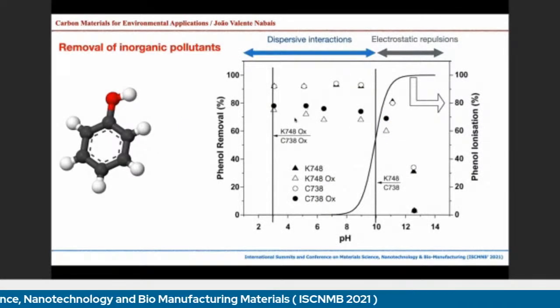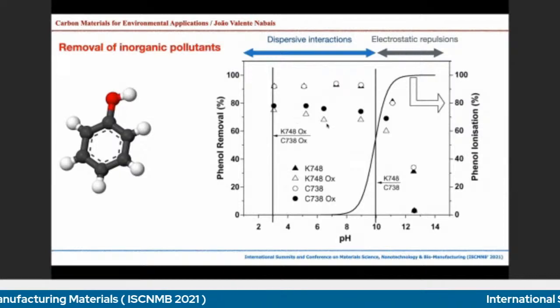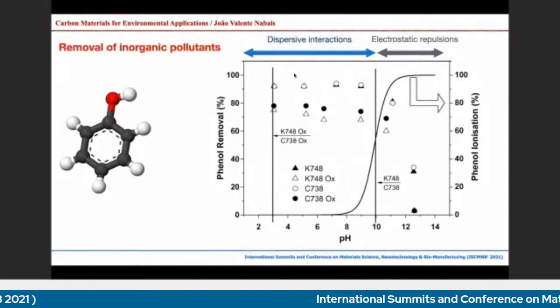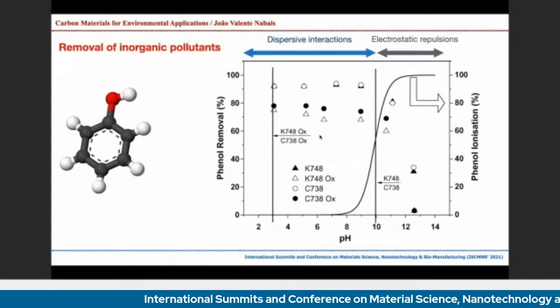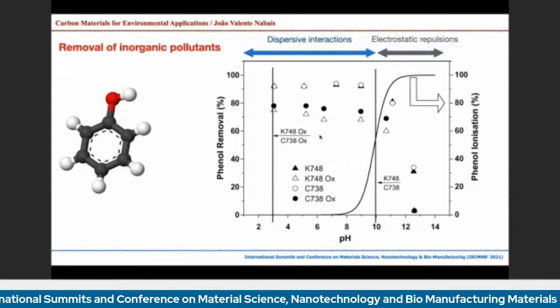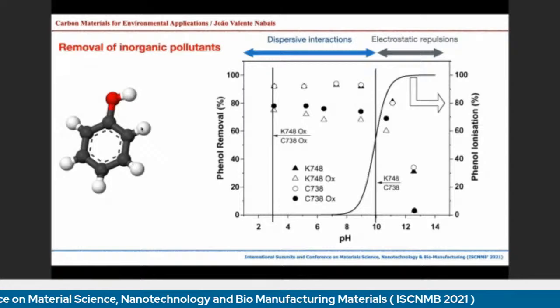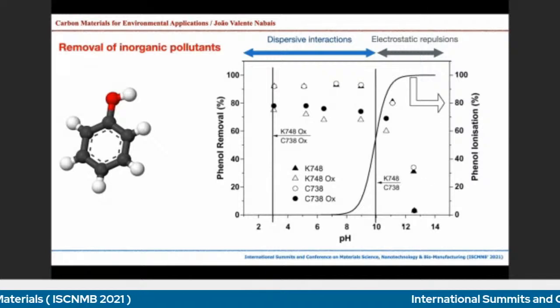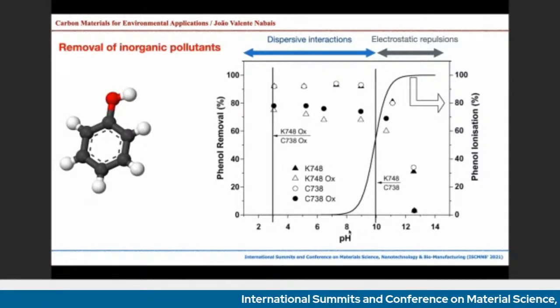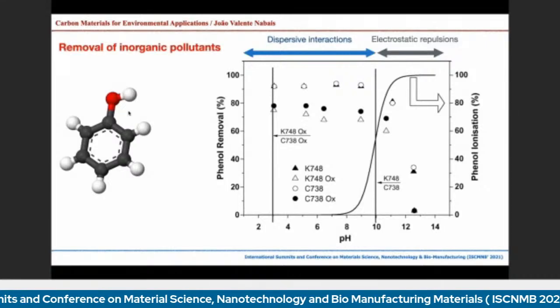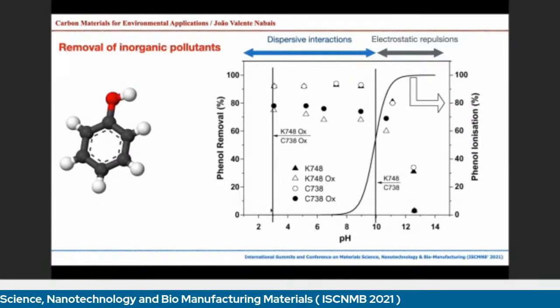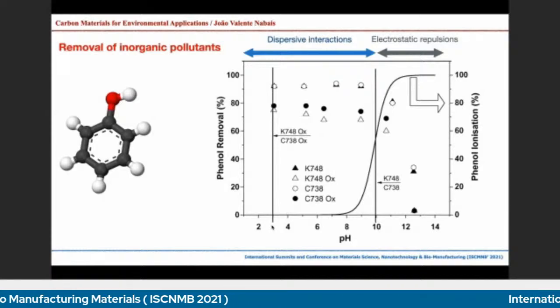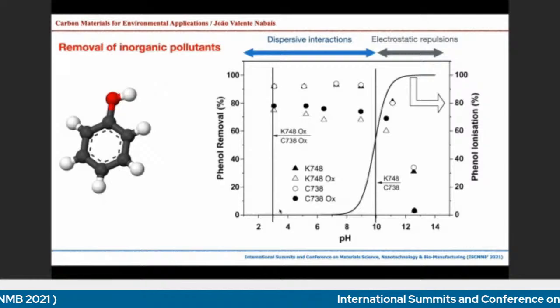This is a more complex figure, but what I would like to point out is that depending on the carbon material, the carbon characteristics, surface characteristics, but also on the structure of the molecule, which is phenol, you can see here this line is the phenol ionization. Well, of course, it is linked with pH. When we increase the pH, the phenol will start to be ionized, so it will pass from a neutral to a negative molecule. The line here is the point of zero charge. So the materials have a negative surface when the pH is higher than the point of zero charge.